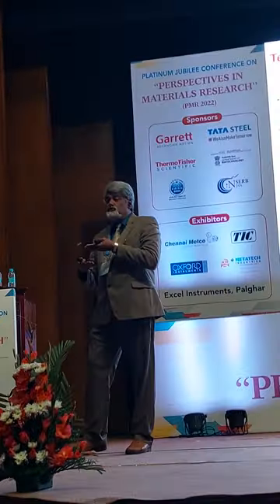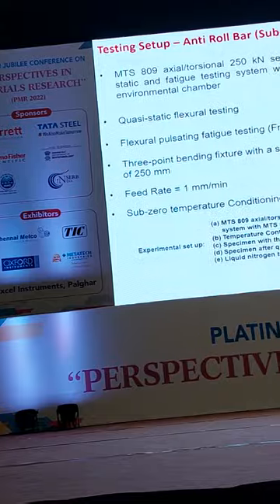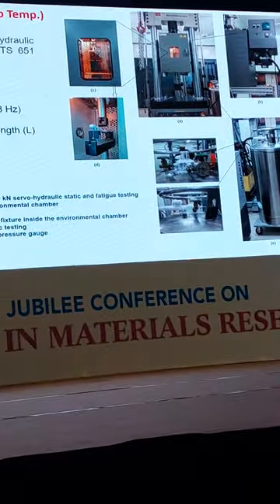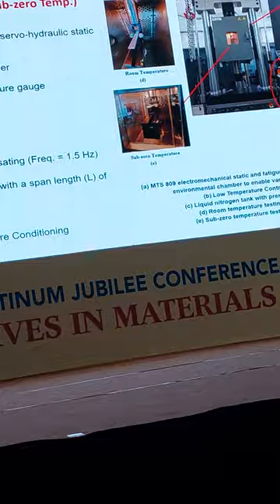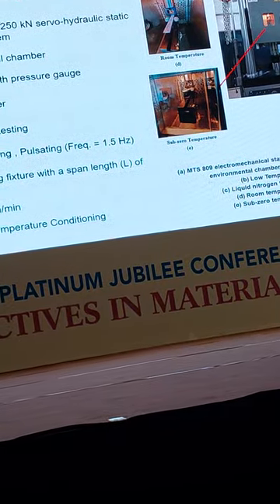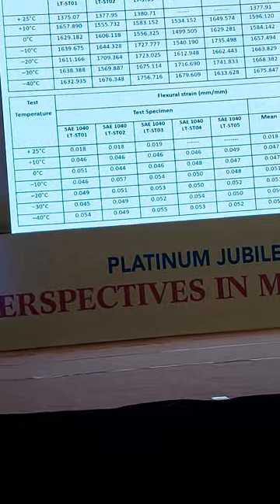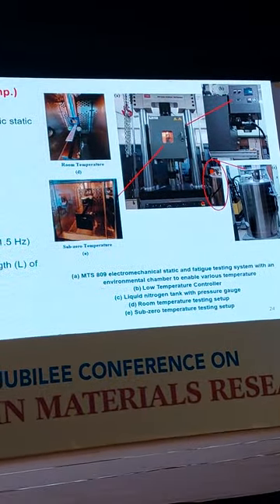Test parameters were deliberately chosen at 1 to 3 Hz for the anti-roll bar pulsating oscillations, reflecting real-life automotive conditions. The setup at IIT Bombay used a load frame for quasi-static tests and pulsating flexural fatigue from 1 to 3 Hz. Samples were conditioned in the environmental chamber for more than 12 hours until saturation equilibration, then transferred to a chamber in the testing machine and re-equilibrated to compensate for any temperature loss during transfer.